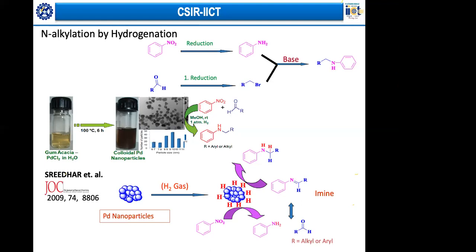But when we look at these nanoparticles, you have these particles here, you have the starting materials in methanol, and at room temperature with a hydrogen balloon attached, you will end up getting this material. No other reducing agents, nothing else. You can separate these nanoparticles after the reaction and then go for the next reaction. So you get the product without generating any waste, and that is the advantage.